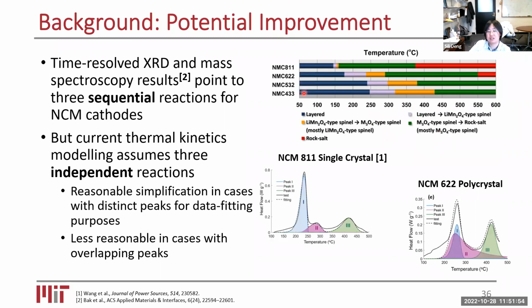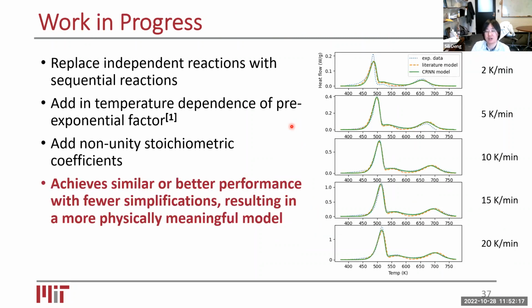We look into the literature for battery materials, it starts as a single material. And if the temperature goes up, the materials start to degrade and to transform into different other materials. So it is not true to assume that these 3 reactions are not related. But currently, if you do not assume that, you cannot do it. So we are wondering if using our CRNN chemical reaction neural network, we can do that.